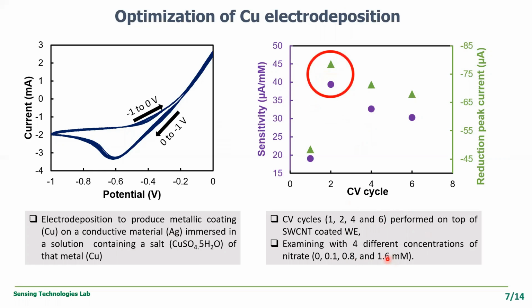And after plotting the sensitivity against the number of CV cycles, it is noticeable that the 2 CV cycle showed the highest sensitivity. Also on the right side, you can see the reduction peak current obtained from 1.6 millimole of nitrate. The electrode with 2 CV cycles of copper deposition also showed the highest current. So more than 2 CV cycles actually covered up all the CNT, and the surface area decreased, and as a consequence, the sensitivity also decreased.